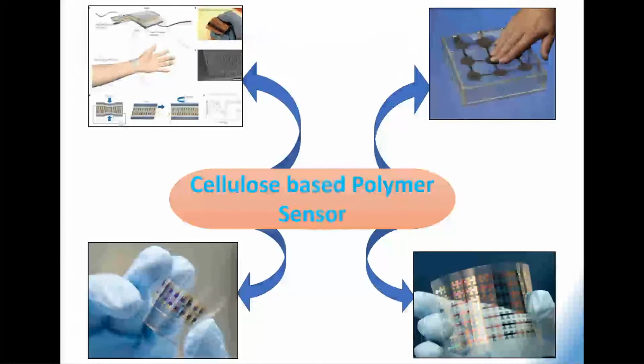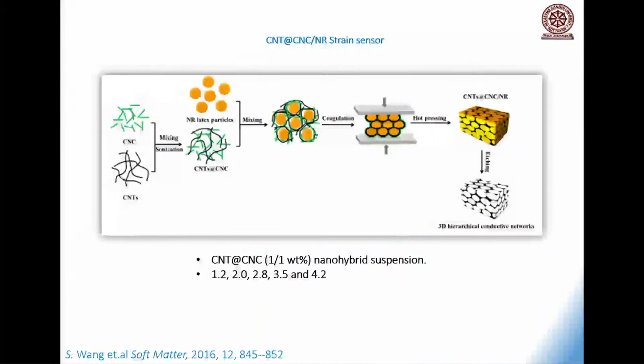We are also into sensors. Nanocellulose makes sensors. Maybe I will show you one slide. You see, this is nanocrystals made from pineapple leaf fiber. And this is carbon nanotube. You can combine them together using natural rubber latex. You mix with the natural rubber latex, you introduce CNT and nanocellulose, you go for a mixing process, you go for coagulation, go for hot pressing, and finally what you get is a 3D hierarchical conductive path. Very simple manufacturing process.